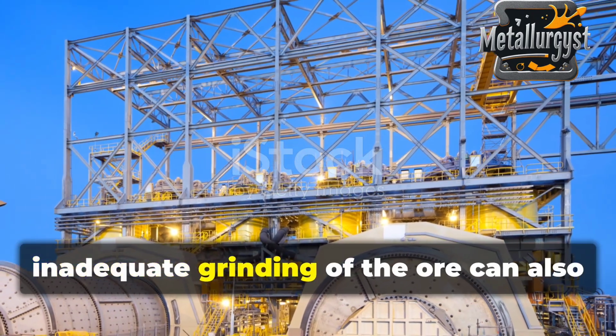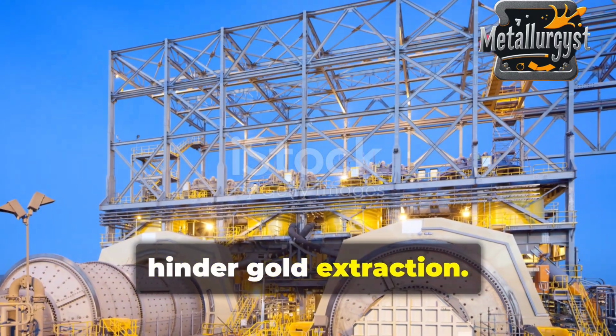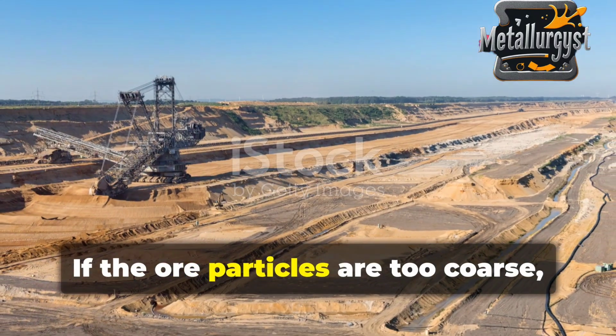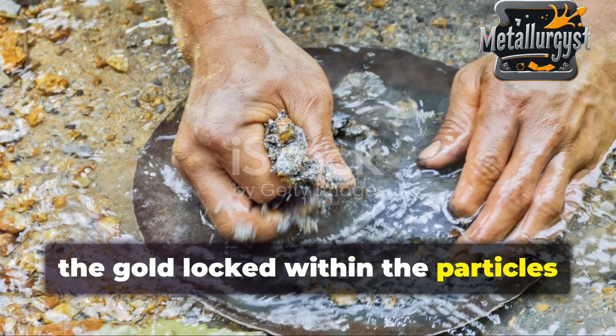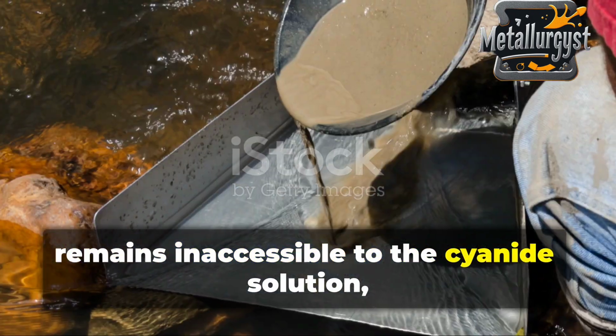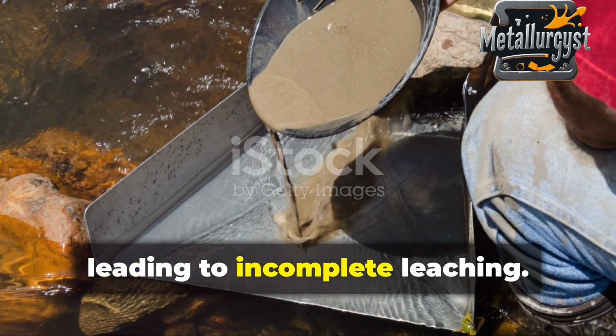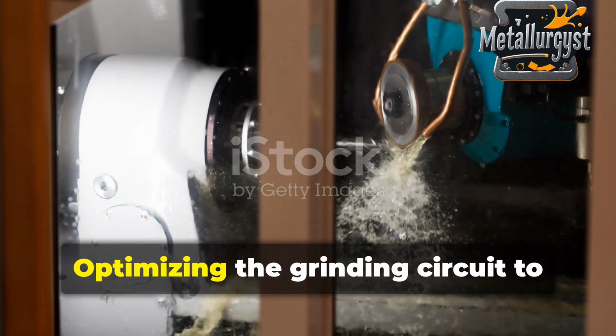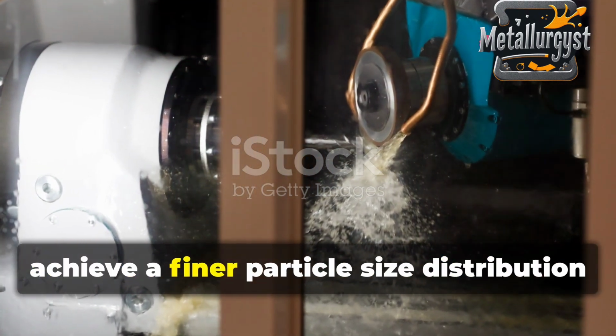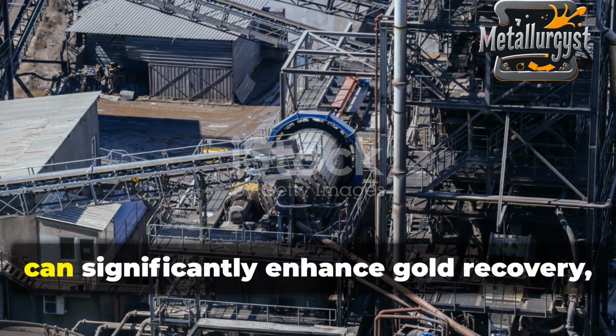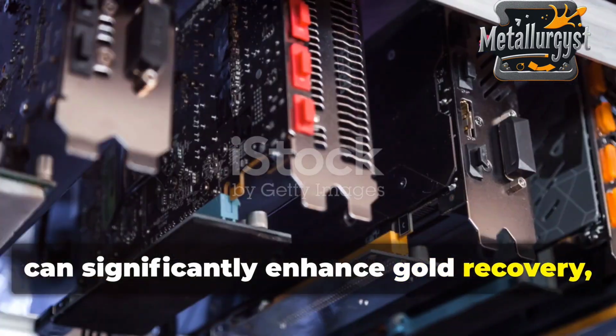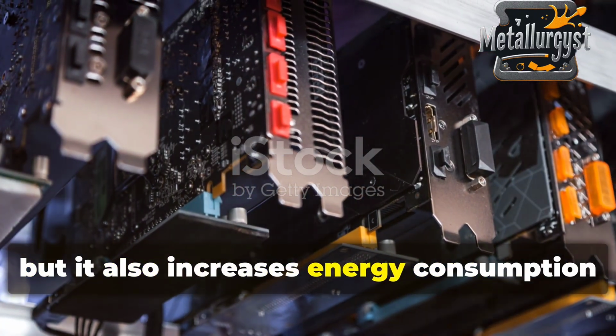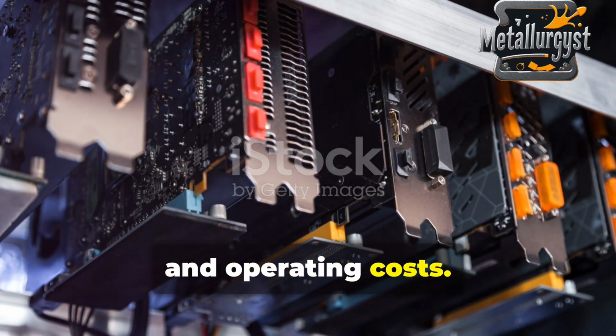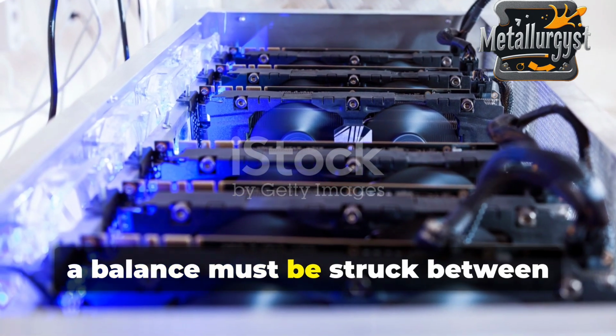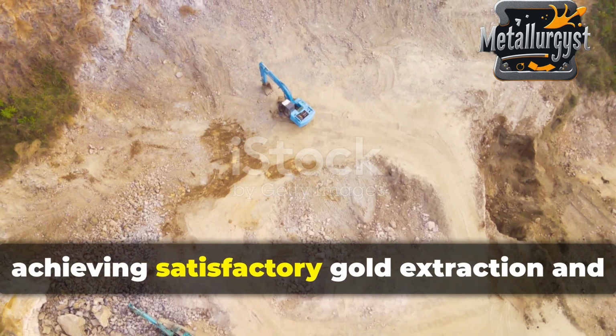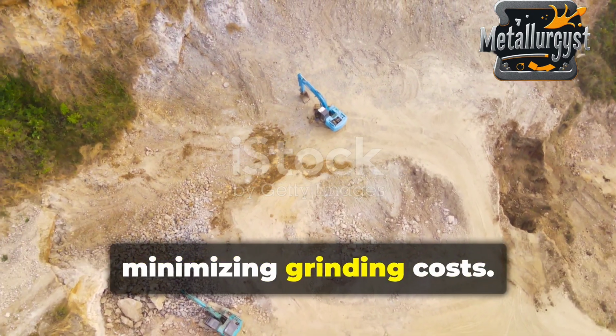Furthermore, inadequate grinding of the ore can also hinder gold extraction. If the ore particles are too coarse, the gold locked within the particles remains inaccessible to the cyanide solution, leading to incomplete leaching. Optimizing the grinding circuit to achieve a finer particle size distribution can significantly enhance gold recovery, but it also increases energy consumption and operating costs. Therefore, a balance must be struck between achieving satisfactory gold extraction and minimizing grinding costs.